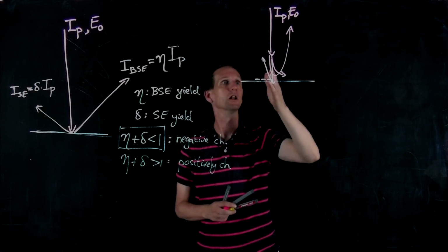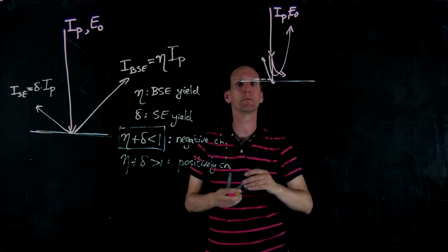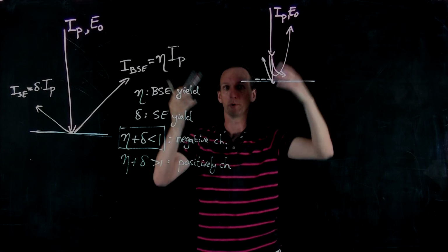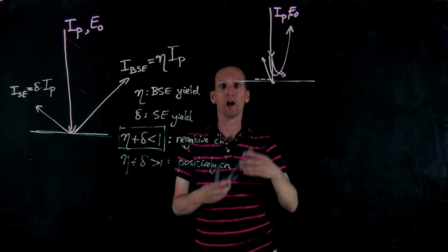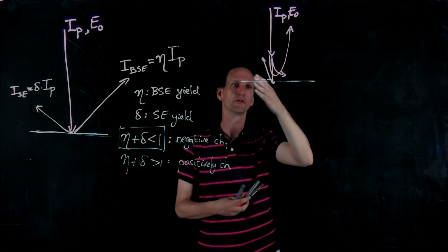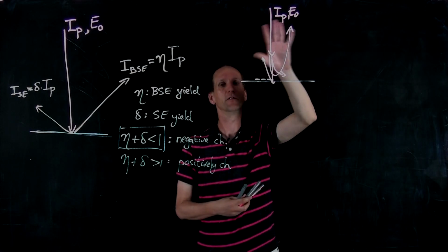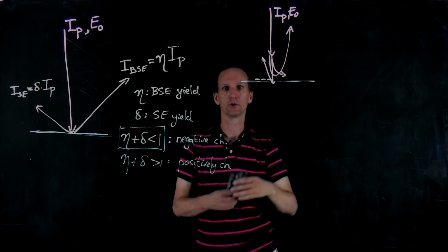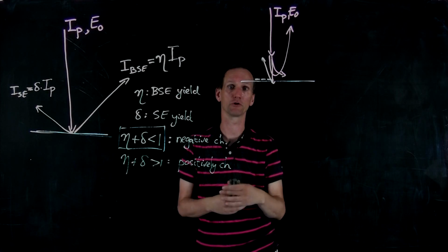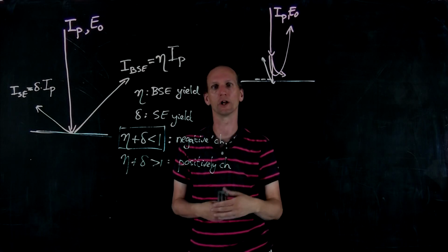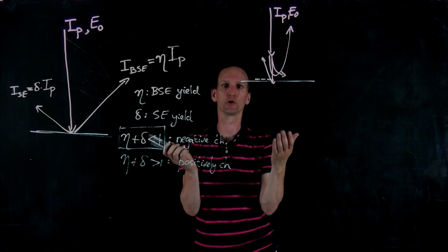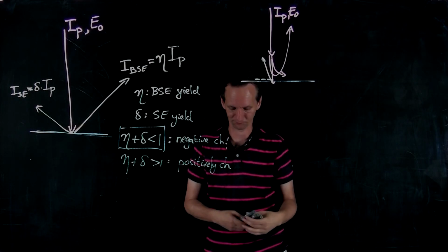So in this case, the electron beam will travel into the vacuum chamber and may actually hit parts of this chamber, the pole piece of the electron lens or parts of the detector, and generate secondaries there. In that case, we may get a signal that resembles, while we are scanning, the interior of the sample chamber of the SEM. So then we get an image that is a mirror of the inside of the electron microscopy chamber. This is a fun experiment to do if you look at a non-conductive sample, and you can really get like a photograph of the interior of your SEM.